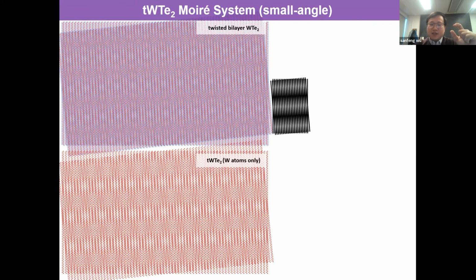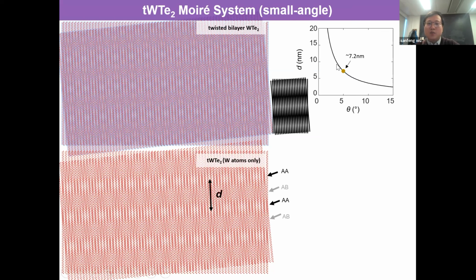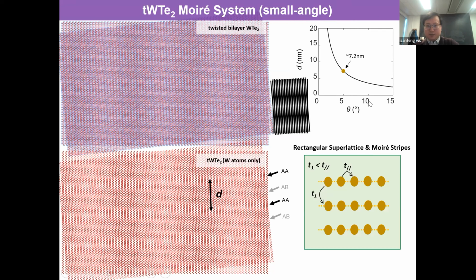So the monolayer has a rectangular unit cell. Here, the twisted bilayer also has a rectangular unit cell, but it's big. And the twist angle will change the size of the unit cell. If you think of it as stripes, it will change the distance between stripes. And we are interested in this talk in a small angle near 5 degrees. Near 5 degrees, the distance between the AA spots, or interlayer spots, the distance D, is about 7 nanometers.